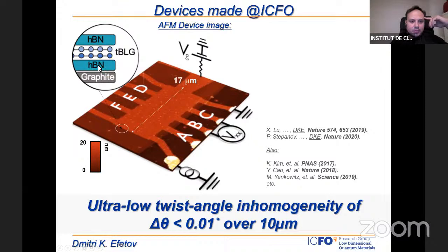We have hBN, which is just an insulator, and encapsulated in this hBN we have this twisted bilayer graphene. What's important now is that we can use the graphite gate for different tricks, and I will talk about this in more detail later. But really what we can do with graphite is apply a voltage to it, and then we can capacitively change the carrier concentration of the twisted bilayer graphene. The capacitance is strong enough that we can completely empty and completely fill the moiré bands just by tuning a voltage.